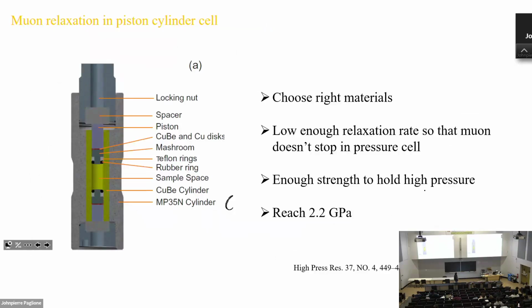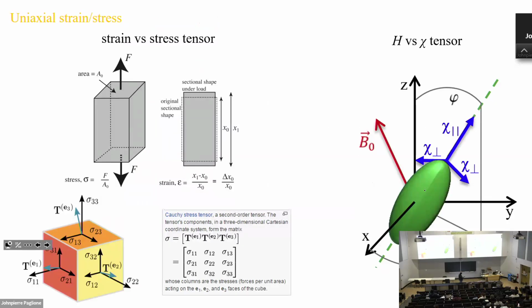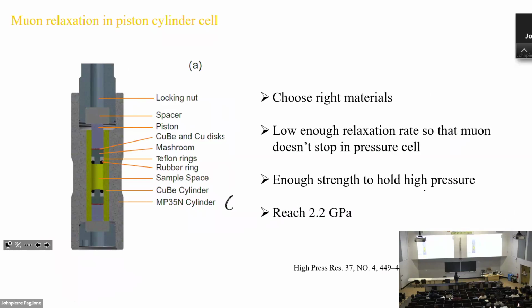Another thing you can do is mu-SR. Here, the key thing is to choose the right material. In some materials the muon will relax more and in other materials less. So they tried different materials, and it turns out this MP35N, the combination of this and the beryllium copper, is the best. Do I have a picture there? Okay, I didn't show the picture there. But with this type of cell, you can go to 2.2 GPa with no significant relaxation of the muon in the pressure cell.